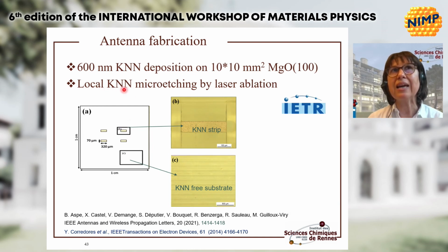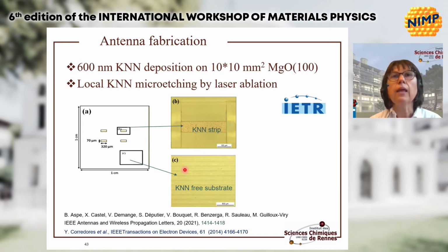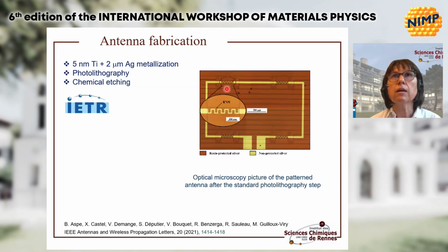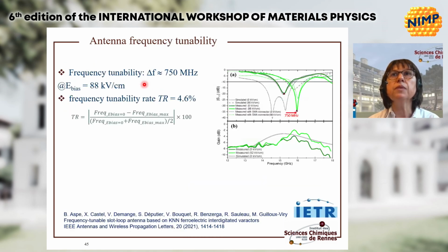we have performed a local KNN micro-etching by laser ablation in order to confine the KNN only below the interdigitated capacitors. Indeed, we have shown in previous works that by this confinement, it's possible to strongly decrease the global loss of the device while preserving the tunability. So after this micro-etching, there is still KNN only below the varactors. After standard metallization, photolithography and chemical etching, the antenna has been obtained and measured.